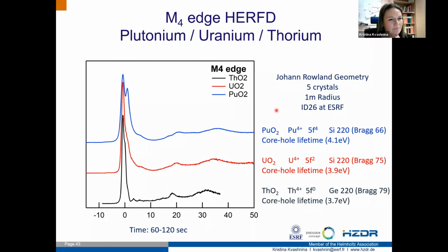I would say it's of course a combination. Thorium is also low in the incident energy. It's 2.9 versus 3.7 keV, so already the incident energy resolution is better. But additionally, the Bragg angle of 79 degrees is of course helping quite a lot. Plus, as I said, because we have 5f0 electrons, this is also not the case as with uranium, where you would really have this kind of interatomic interaction of the 5f state. Well, sure, but that's not instrumental. No, exactly, right.